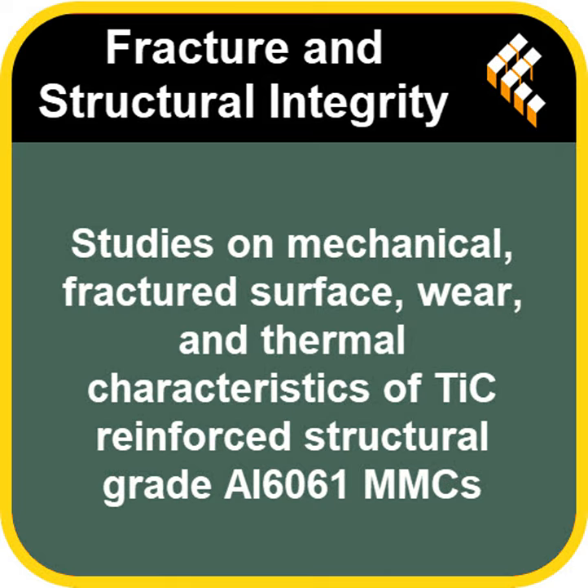So cleaner wear tracks. Exactly. The unreinforced sample showed tracks with much larger amounts of gouged-out material and debris. The SEM images really highlighted how those TiC particles helped create that stable, protective surface under applied stress, significantly enhancing wear resistance. That's an incredible multifaceted benefit.